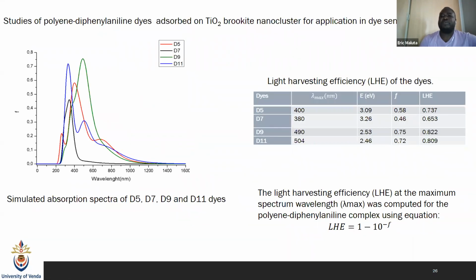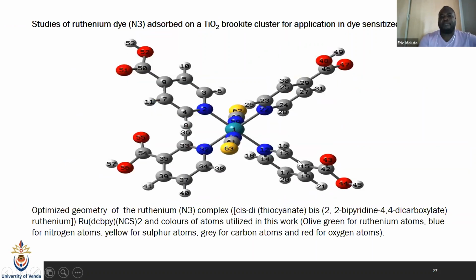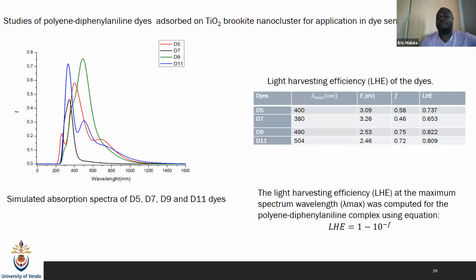But then for the properties, we look at the absorption spectrum of these different dyes, and then we also calculate their absorption efficiency, the light harvesting efficiency, which is calculated by this formula here. At each highest wavelength, from the figure on my left here, where there's a cursor, we can see that each of the dye molecules, D5, D7, D9, and D11, has its own highest wavelength, which is the lambda max here on the table. Then we can calculate their light harvesting efficiency using that formula there.